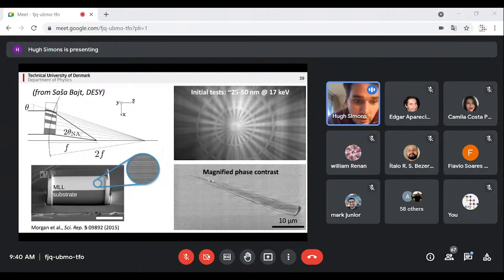They're incredibly small. I think the scale bar here is about 10 micrometers. So they're tiny, tiny lenses, and they have to move very close to the sample. But at least the initial tests we've done give us a resolution of something close to 25 to 50 nanometers, which is 3-4 times as good as what we can currently do. And the latest tests have been getting closer to 5 nanometers.